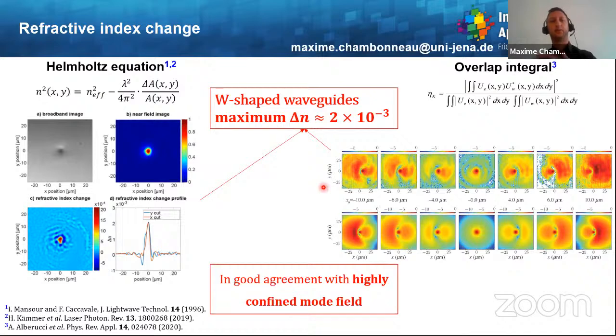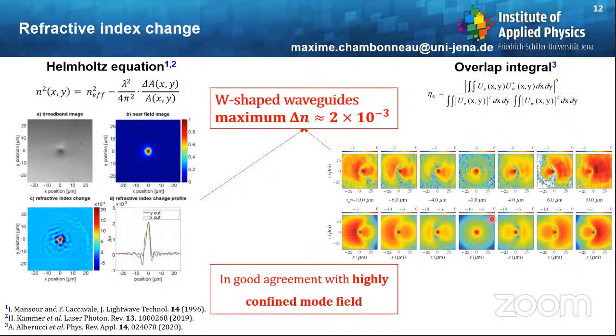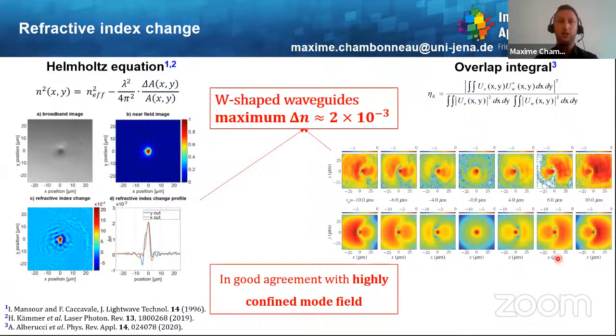With the positioning system we have, which is a piezoelectric stage, we could take different images when we shift the waveguide with respect to the incoming light and then perform the same simulations. As you can see, it's working pretty well on this figure. So both methods we have employed allow us to conclude that the waveguides are W-shaped with a maximum refractive index change around 2 × 10⁻³, which is in very good agreement with highly confined mode fields.